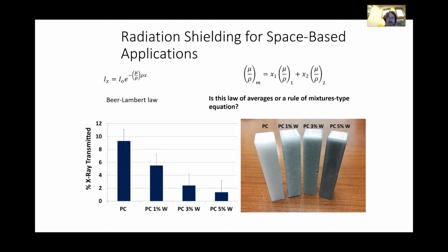Here are some results. We have our straight polycarbonate, which was white in color. When we add 1% by weight tungsten, it starts getting darker, and we were only able to go up to 5% since tungsten is very hard, and we didn't want to eat the inside of our extruder, so we didn't go higher. Polycarbonate on its own already blocks X-rays pretty well, which is kind of interesting.